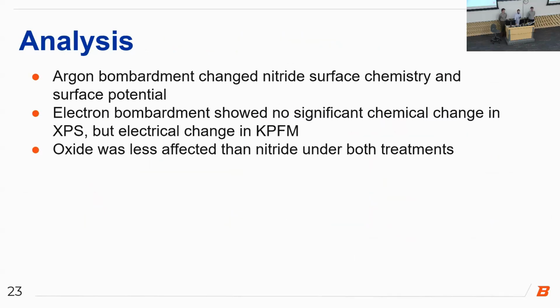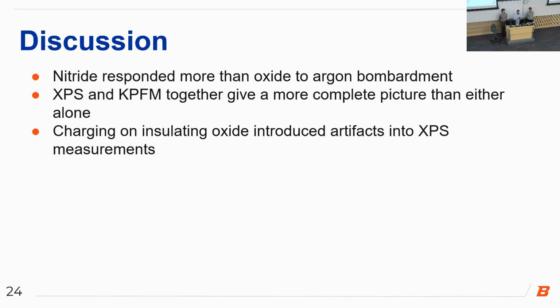To connect everything together, for argon bombardment, XPS and KPFM are telling us the same story. The nitride surface chemistry changed and its electrical behavior changed too. The oxide showed much less change in both. And for electron bombardment, XPS showed no significant chemical change in either film, but KPFM detected an electrical response in the nitride. A few things are worth discussing. First, silicon nitride was more responsive than silicon oxide across both treatments, and the 2 treatments affected the films through different mechanisms. Argon changed both chemistry and electrical behavior, while electron bombardment only showed an electrical effect.